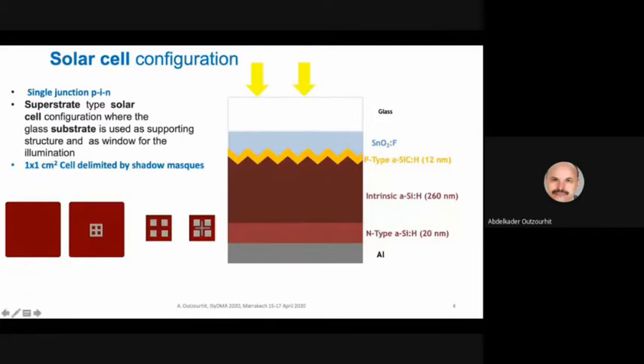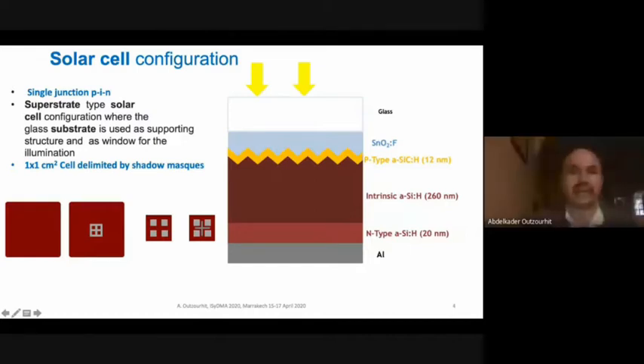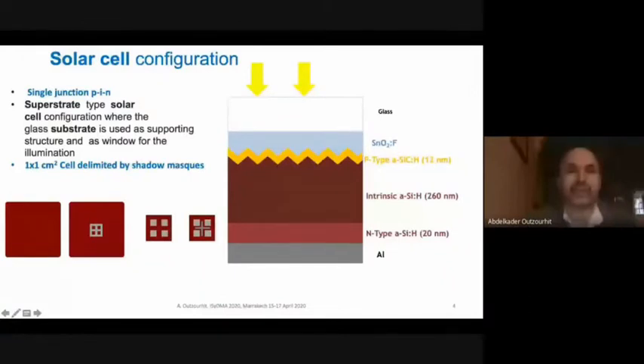The cells were delimited using metallic shadow masks on very large substrates that were used to deposit the thin films. These substrates are 20 by 20 square centimeters, and the active area of the cells that were delimited by these shadow masks is about 1 by 1 square centimeter.